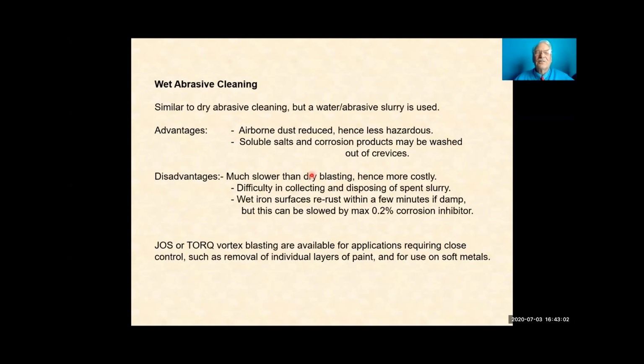Of course, the disadvantage is that you're making it wet, and so it's got to dry because it will re-rust. It is slower than dry blasting. You can actually try and prevent the rusting by putting a corrosion inhibitor in with the water, so that works quite well.